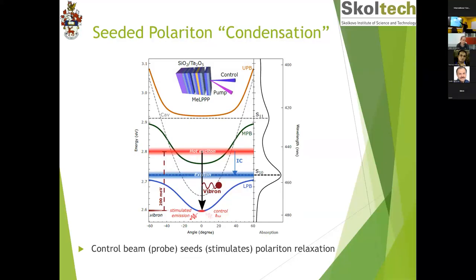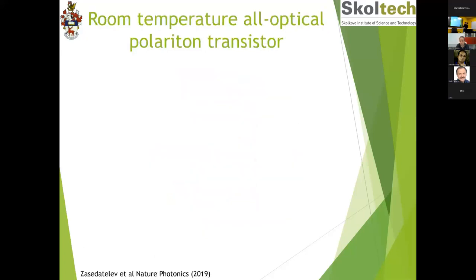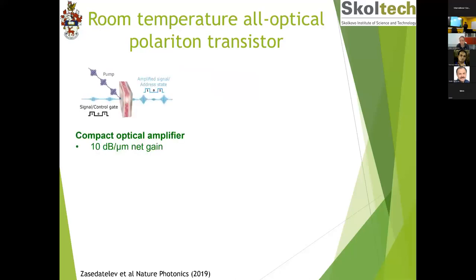So we inject hot excitons, one vibron above the ground polariton state. And then we are looking here for condensation. We can stimulate this condensation, so we can create amplification, if you like, by sending a few photons which are resonant to the ground polariton state. And now, if we do that, and we go for a room temperature all-optical transistor, we could show that we have all the characteristics that you would like to have for a transistor. So we have compact optical amplification with the highest ever reported optical gain, 10 dB per micrometer net gain in the system.